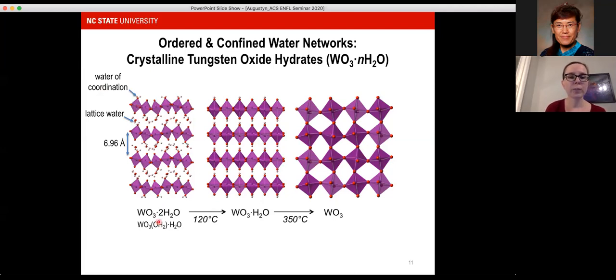If you take this material and heat it at 120 degrees Celsius, you will go through a structural phase transition, so it's very well defined, with the loss of that lattice water. And then if you go to an even higher temperature that's required to remove this water of coordination, you will form the anhydrous tungsten oxide, also through a phase transition. So all the crystalline structures for these three materials have been solved.